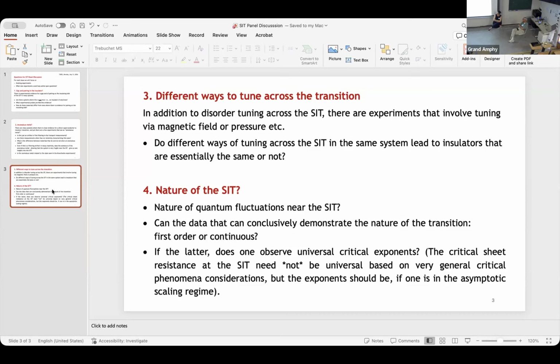That seems to me not obvious, but it's also different from the zero field case where we have proliferation, we have these vortex anti-vortex pairs that are bound, and we increase this disorder, you may have more and more because superfluid density is dropping. Then suddenly we lose superconductivity, but the vortex glass is certainly a different animal to take into account. Another energy scale may happen.